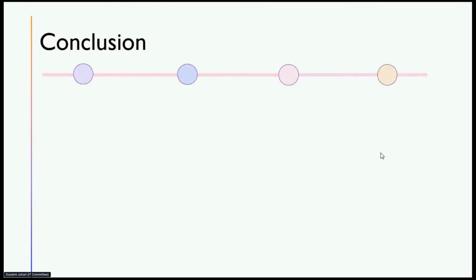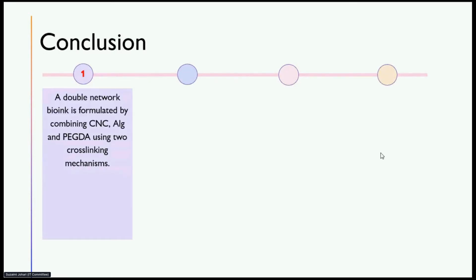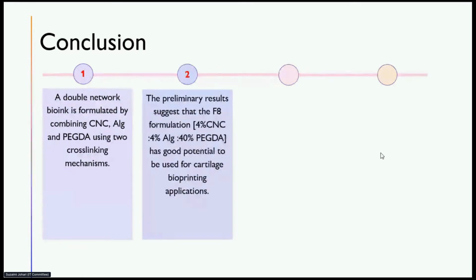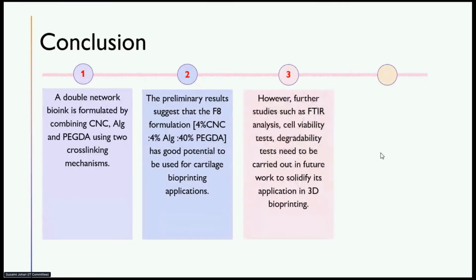Next slide. So in conclusion, first we were able to formulate a double network bioink using CNC, alginate, and PEGDA. Second, based on the preliminary results, it is suggested that the F8 formulation shows good potential for cartilage printing application, so it can serve as a guide for future studies if you want to optimize this bioink. Third, this project is still very early in its progress and needs a lot of further tests, so we should conduct further tests like FTIR analysis, cell viability tests, and degradability tests to solidify its application in bioprinting.